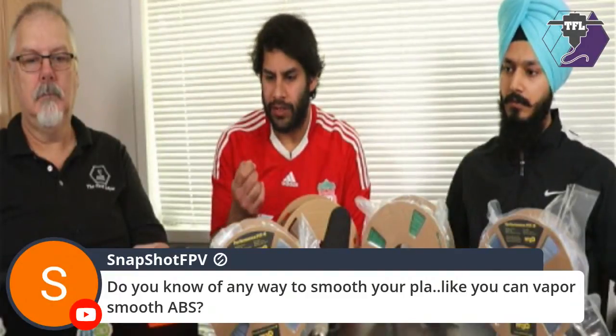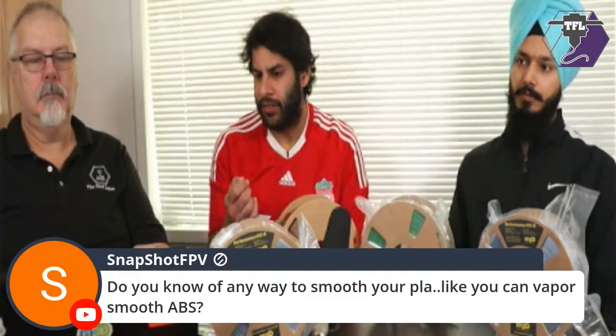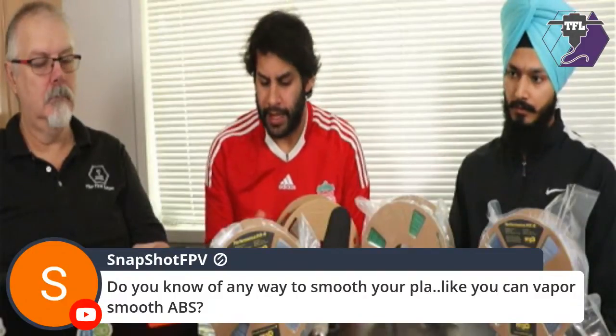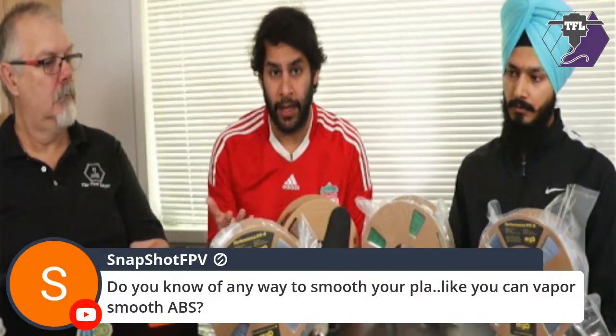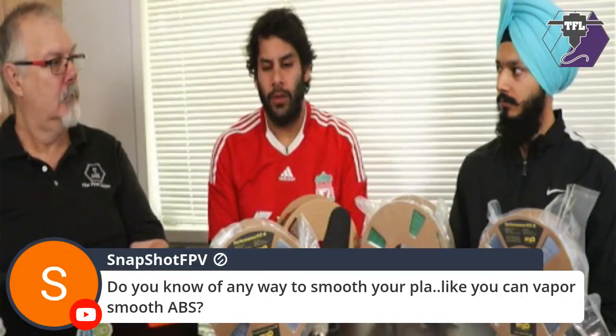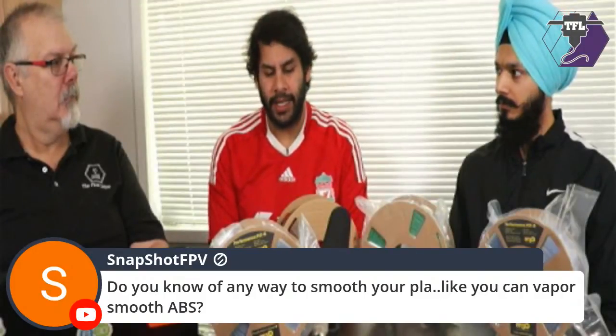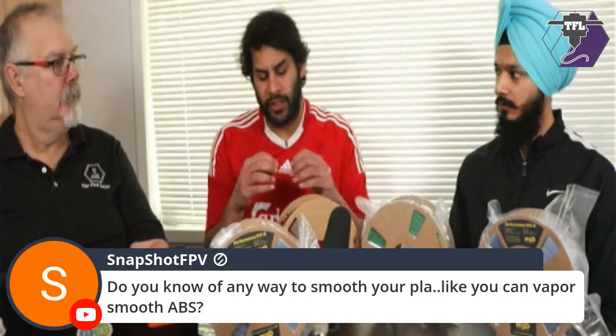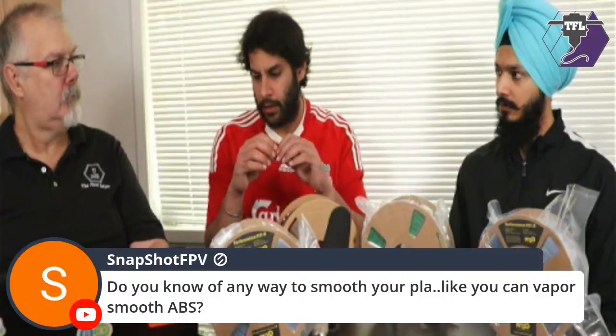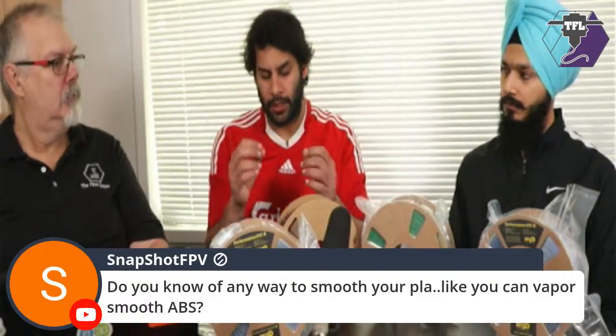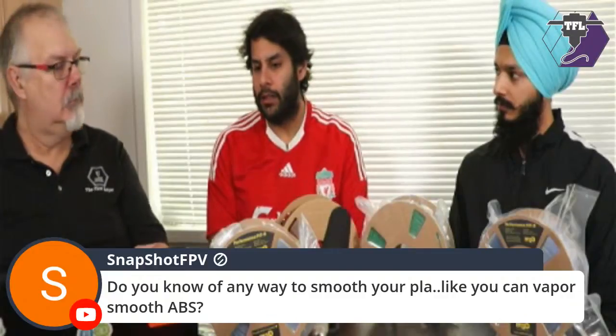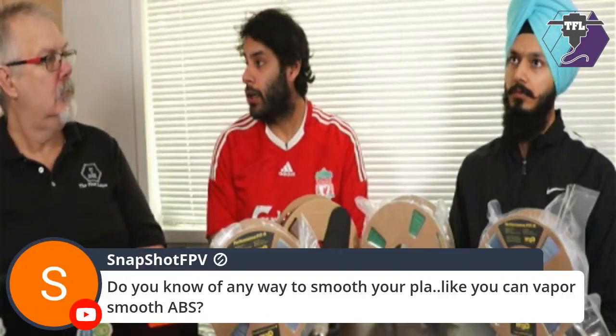It's known for its high crystallinity. It's like 99% crystalline, and that is what gives it its mechanical properties. And when you boil it, you're not only smoothing it out a little bit, because what you're seeing is micro swelling around the surface or the interface between the water and the material, but you're also annealing it and making it much, much stronger.